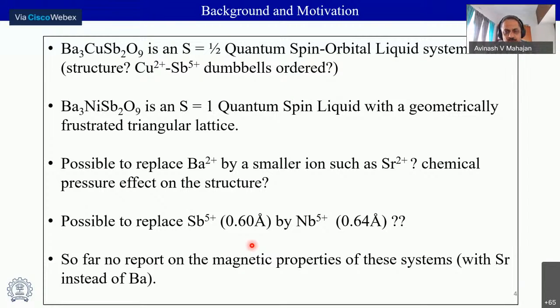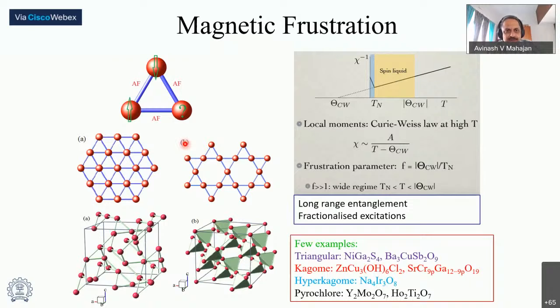So with this sort of motivation, we worked on the strontium copper antimony oxide system and also the niobium one. I'll present here data associated with the antimony-based system. So the basic introduction to magnetic frustration is contained in this slide. As Sampath already mentioned, if you have Ising spins on a triangular motif, there is this associated geometric frustration because you cannot satisfy all the spin interactions simultaneously.